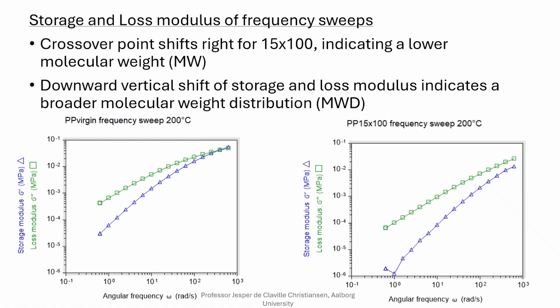If we do oscillatory measurements and plot it in a little bit different way, where we plot the elastic response versus the viscous response, the loss modulus G double prime, that is the green curve, and the blue, that is the storage modulus G prime. Then you can see on the left-hand side a virgin material, and you can see a crossover point on this curve. This crossover point disappears when it's 15 times recycled on the right-hand side. And that means that the molecular weight distribution has been broader on one hand, but it also means that you have a shortening, a lower molecular weight distribution.